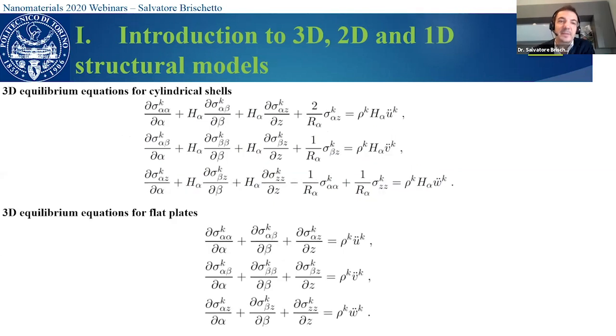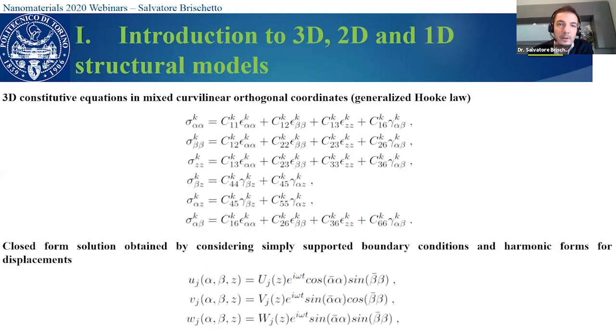Then these equations can be simplified for cylindrical shells by considering infinite R beta radius of curvature and the parametric coefficients H beta equal 1. And then considering also the other radius of curvature is infinite, we have the typical three-dimensional equilibrium equations for flat plates, as you have seen in all studies, papers, and so on. Now, the second step is to consider the generalized Hooke law. So we have the Hooke law for the three-dimensional case, written for each k layer, okay?